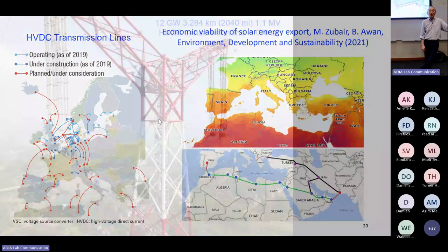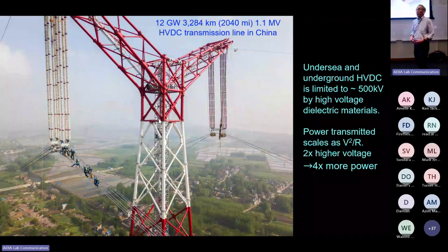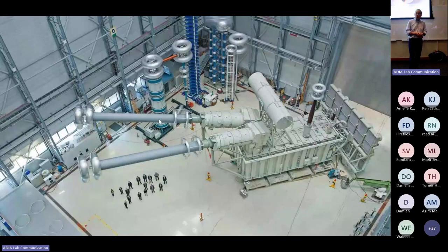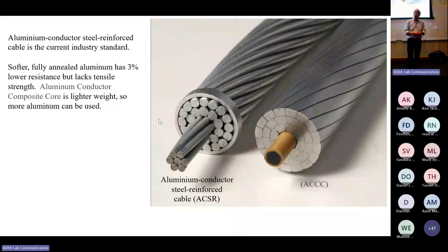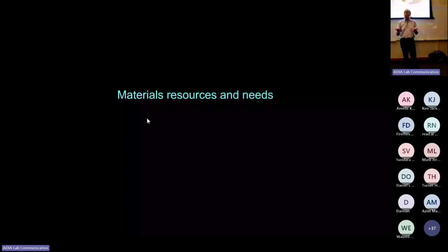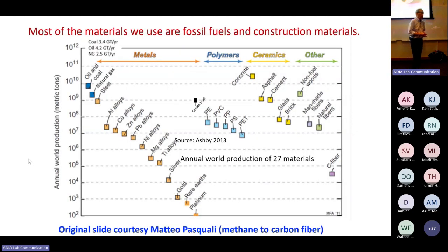And another thing, and this is very interesting, is that the wires that carry this tremendous amount of power are not copper, they're aluminum. Aluminum's a lot lighter. The current wires have a steel core. Steel is not a good conductor, but it gives you tensile strength, so you can string the wires between the towers. Under development and beginning to be deployed is a carbon core with a space-filling aluminum that's now annealed, so it has higher conductivity. So this is in the offing, but there's something significant about this.